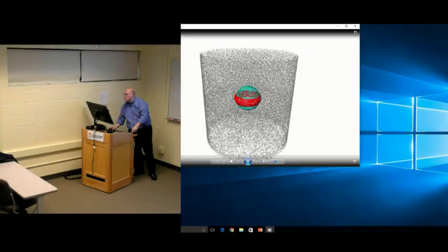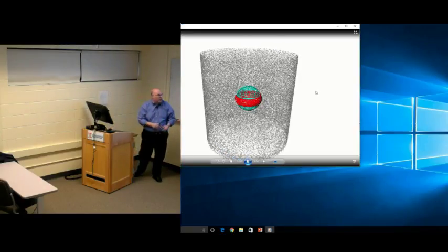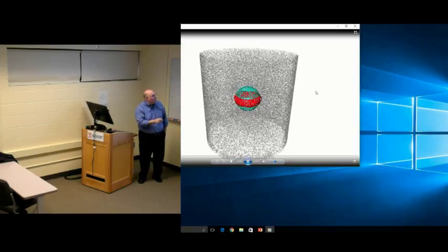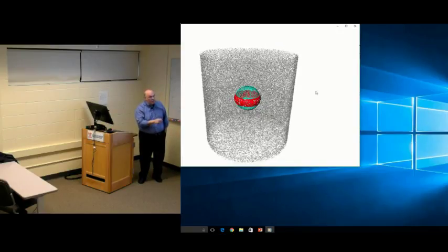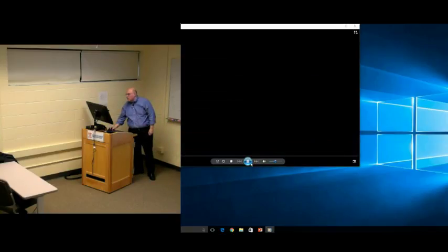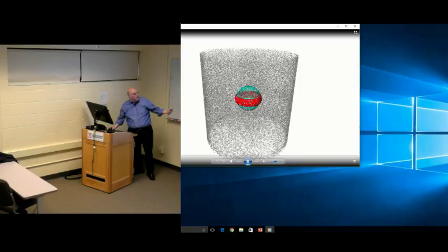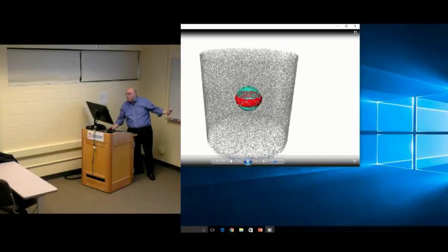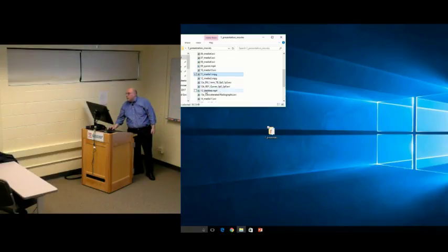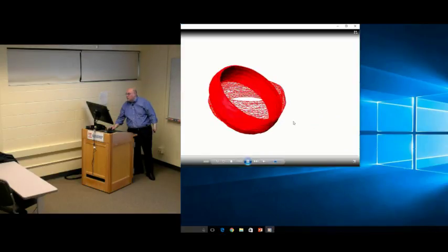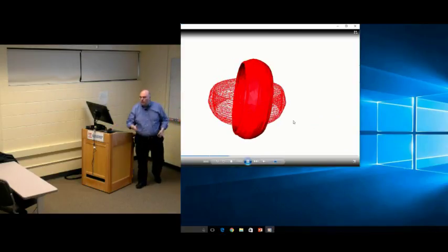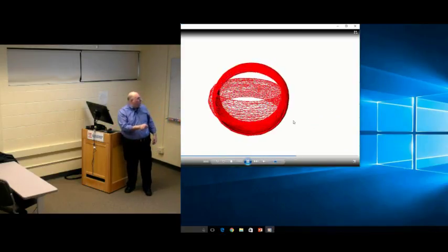It's this one. Right. So we can isolate from the 3D reconstructions the region of debonding, and we do this through image processing. And basically, it's this region around the equatorial plane. And we can actually, in fact, get an XYZ location of this debonded region.